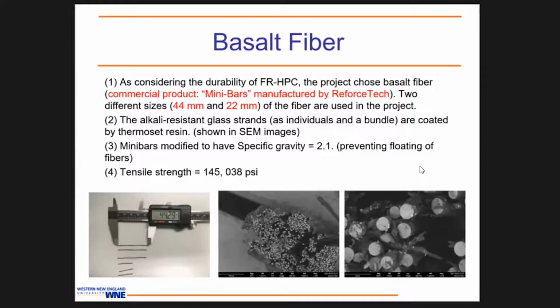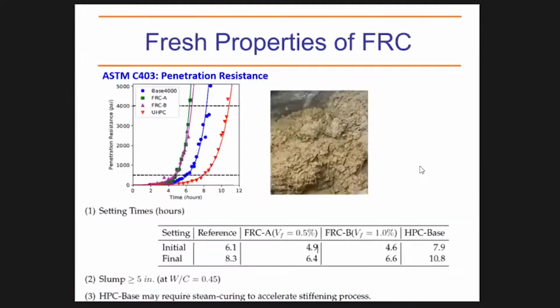And then the tensile strength was given to us as a spec of about 145,000 PSI. So what we did first is the fresh properties, which are setting time as well as flowability or workability. When you have fibers, the surface area increases, so that might reduce the flowability or the workability. So we try to see how much setting time you're going to get, how much slump you're going to get.